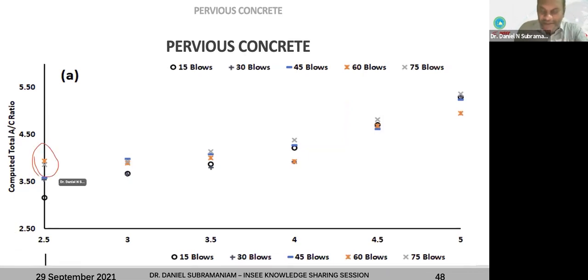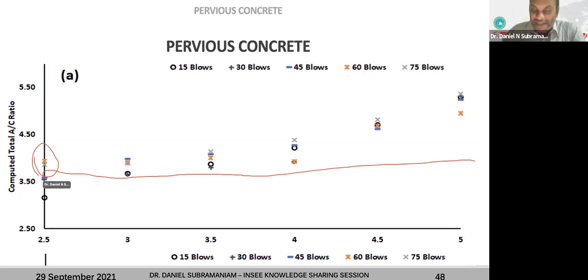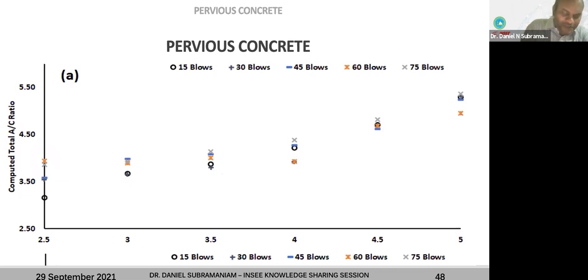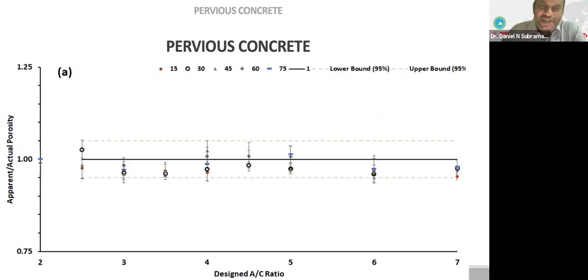Right? So you can see everything. So beyond 4, it's going to increase anyways, because the binder will not exit the surface, right? So now this is, I think, one of the important things that we found out, because there's no point doing anything less than 4 AC ratio, and you're not going to get the permeability also. So when we did the adjustment, we found that they are all somewhere around 4. So they actually come to now apparent versus actual porosity. Earlier we had a bit of a less in the lower AC ratios, but then we found out that everything comes into the 95% confidence interval within that interval itself, right?